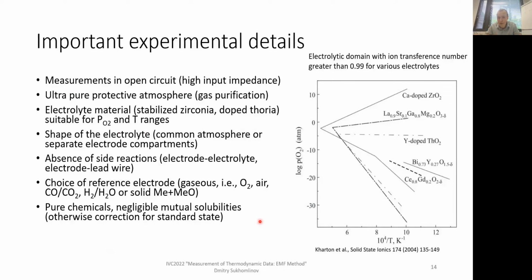But over decades, from the 1950s, since the time the EMF method was introduced for this type of studies, different designs have been tested. For instance, just discs or pellets of solid electrolyte being used, and then both electrodes were, for instance, metal-metal oxide mixtures. Let's say nickel-nickel oxide on one side, copper-copper oxide on the other side. And there is a drawback in such design, because through the gas phase, oxygen will be oxidizing the side which has lower equilibrium oxygen partial pressure, affecting accuracy of the measurement.